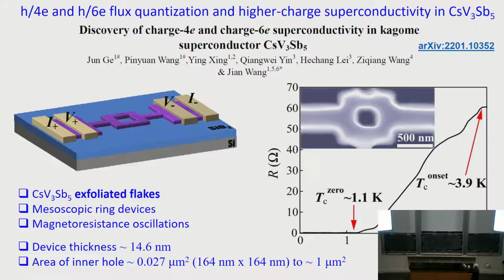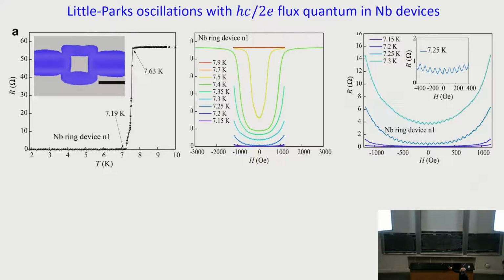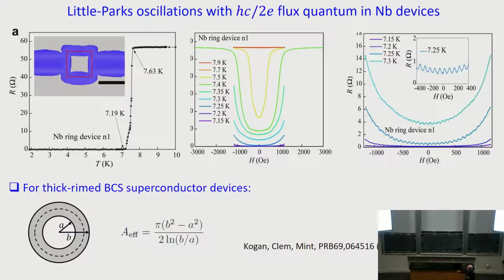So before I show you their data, I want to convince you this device, which looks pretty crappy, right, can produce Little-Parks oscillation. So here you use niobium, a conventional superconductor. Looks pretty ugly. You put the field on. First of all, the transition is really sharp here, right? And then you put the field and you look at just around this temperature, you see these oscillations in magnetoresistance. And the periodicity is precisely corresponding to a charge 2e flux, so long as you use this red rectangle as the effective area. And this was actually shown theoretically: if you have a thick rim structure, the area you should use is in the middle. Right? This was pointed out like that.